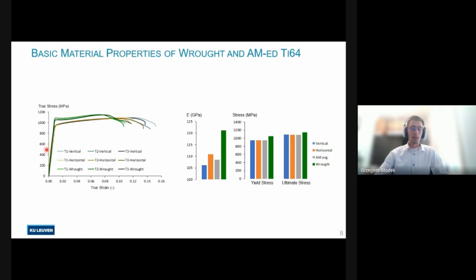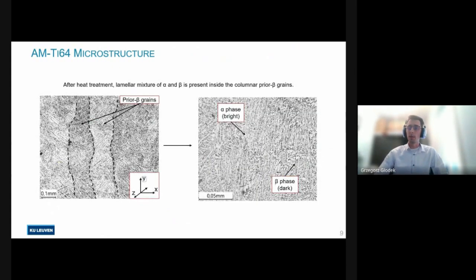So here we can see the stress strain curves of the wrought and the additively manufactured material. As you can see, the additively manufactured TI-64 has both lower stiffness and lower yield and ultimate tensile stresses than the wrought material, but it has somewhat higher ductility. The strain before failure is higher, as you can see here. Now, the microstructure is also pretty standard for additively manufactured TI-64 that underwent heat treatment below its beta transus temperature. So the columnar prior beta grains are still relatively clearly visible, and the microstructure consists of a mixture of lamellar alpha and beta phases.